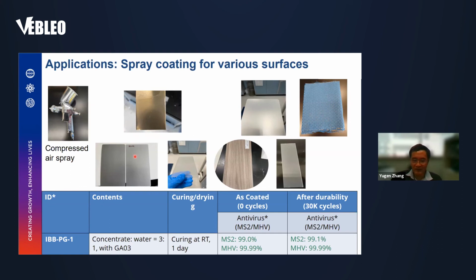And after the coating, the materials really demonstrate excellent antimicrobial properties. And showing here, you can see the coated one can kill both the MS2 and the MHV. And after 30,000 times of durability test, as an abrasion test, the materials still have very good antivirus properties.